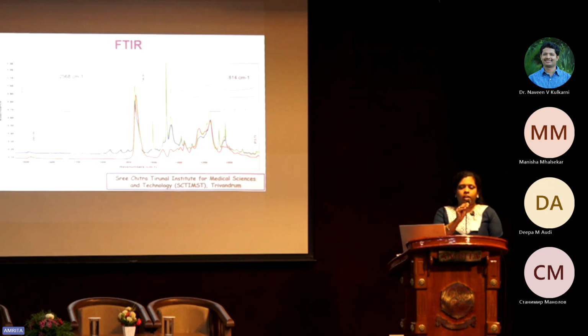And then we have used different characterization techniques in order to confirm the thiol functionalized nanogel and the thiol groups in the system. So at different time periods, we have taken the FTIR, Fourier transform infrared spectra, and the 814, that is the acrylic peak, the CH bending peak. As the reaction progresses, the peak intensity is reducing, and at around 48 hours, it's almost nil. But in the case of thiol, the SH peak still remains after 48 hours. That shows the presence of free thiol group, even after the completion of the reaction, in the nanogel.